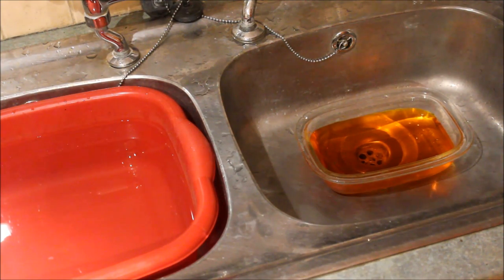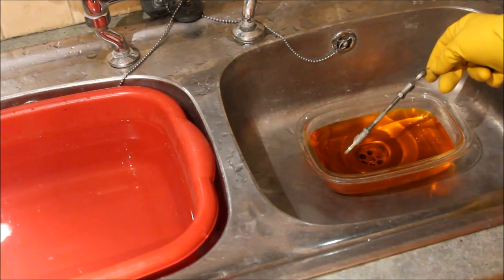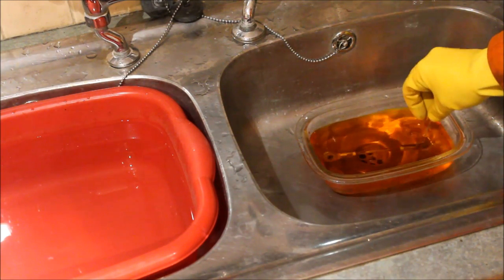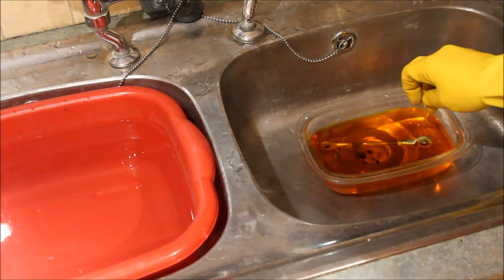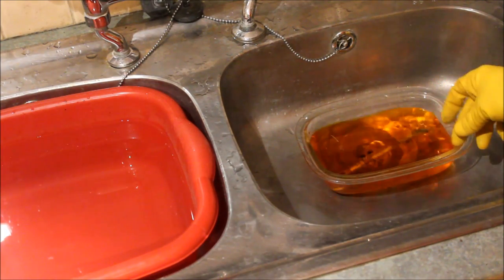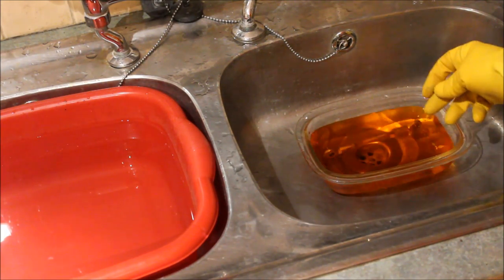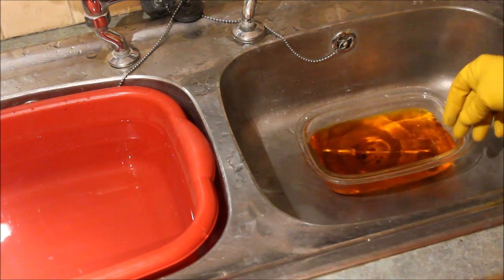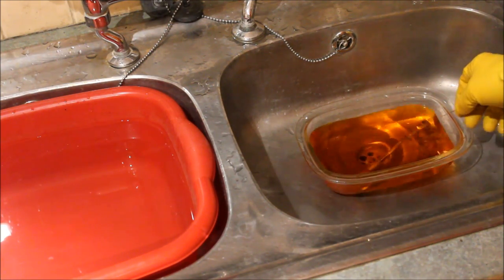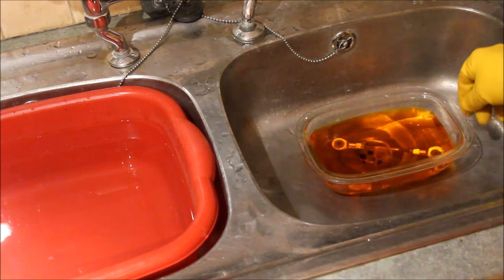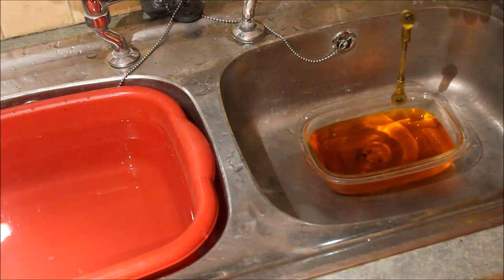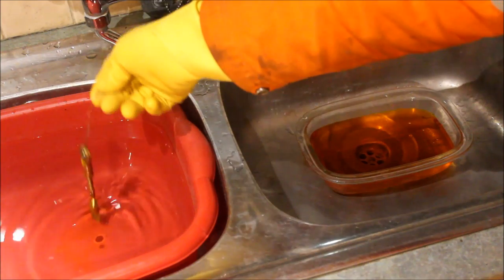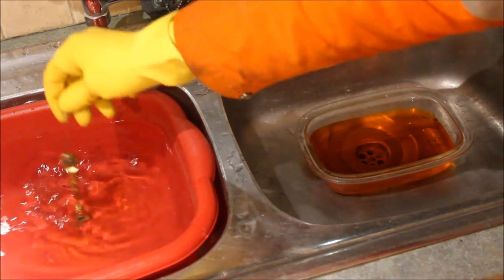So all we then do is get our part, and this doesn't take long. All we're going to do is dip the part in there and agitate it for between about 10 and 20 seconds, again depending on how strong you want that yellow colour to be. Pretty good. And then just rinse it off, don't touch it, but just rinse it off in water, and then